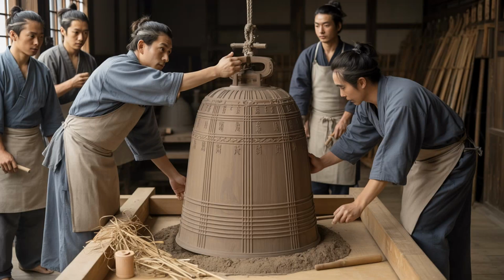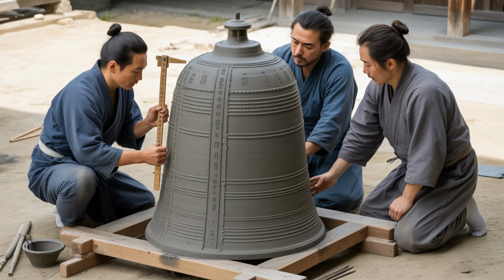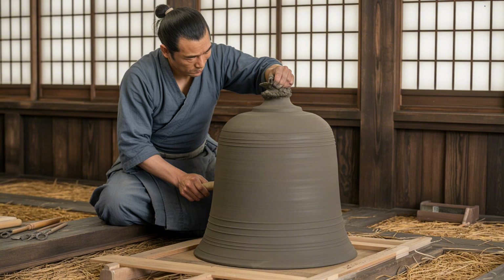The real magic started when they used this wooden model to create the mold. This wasn't your typical pottery class project. The mold consisted of 2 main parts, an inner core and an outer cope, and the space between them would determine the exact thickness of the bell's walls. Getting this spacing perfect was crucial because the wall thickness directly affected the bell's tone. Too thick, and the bell would sound dull and lifeless. Too thin, and it would crack under its own weight or produce a harsh, unpleasant ring.